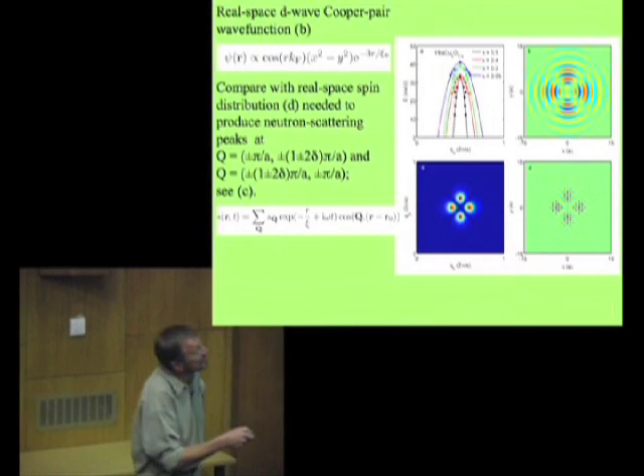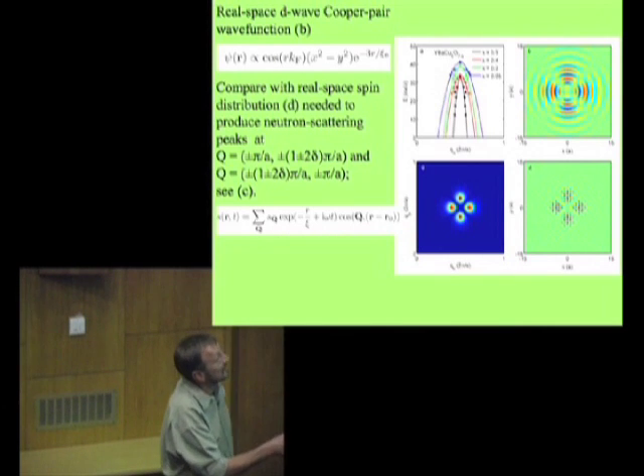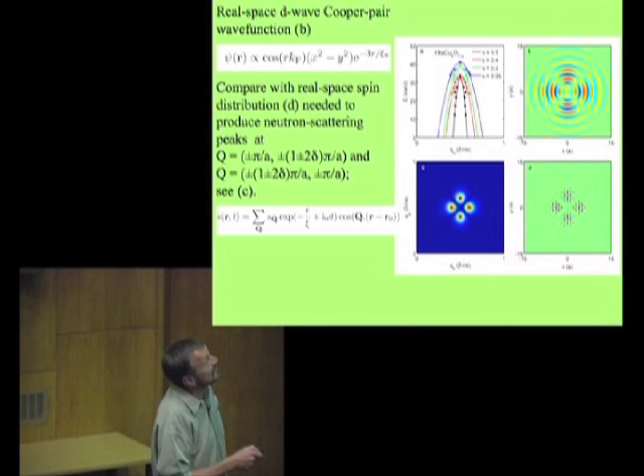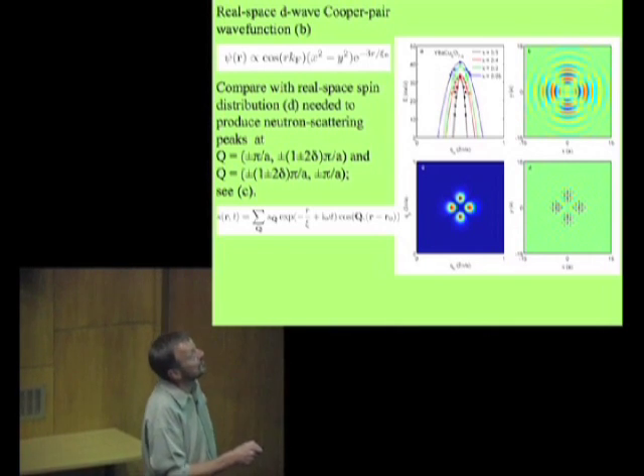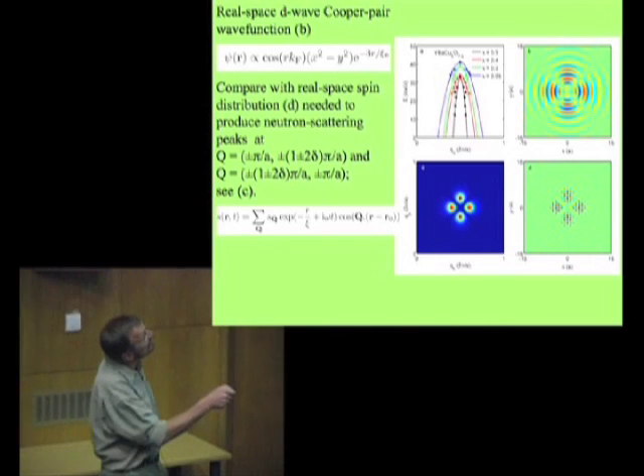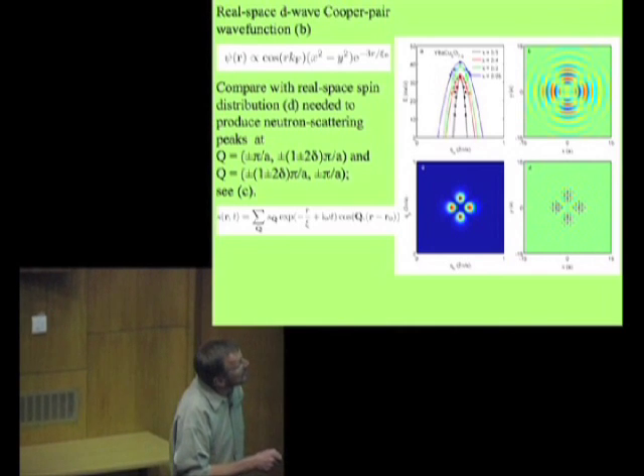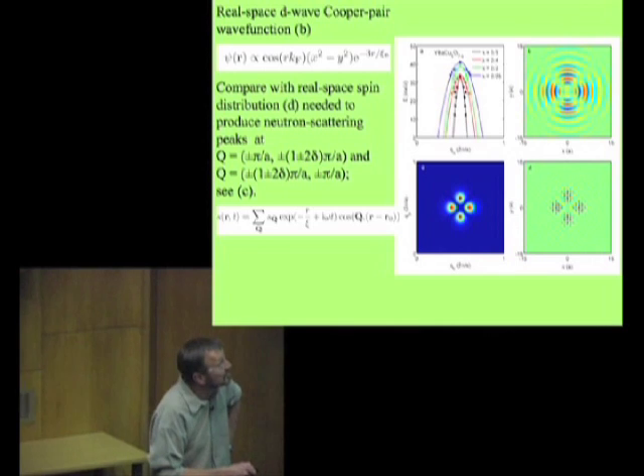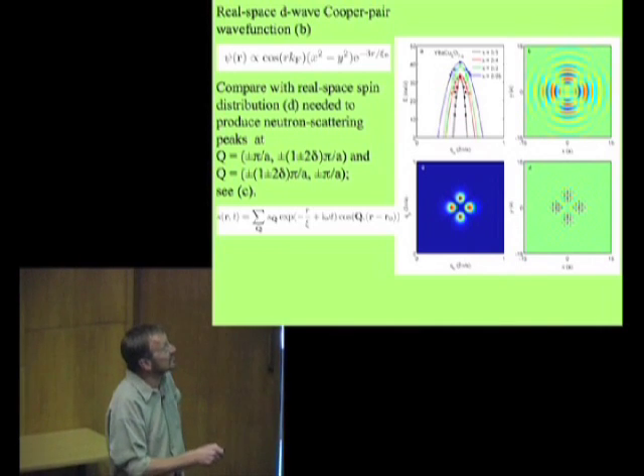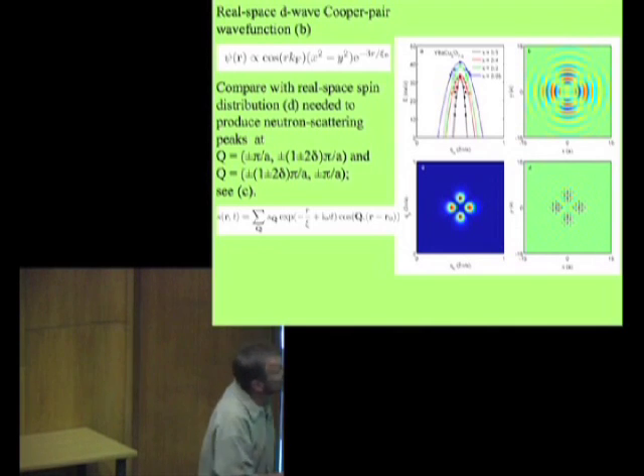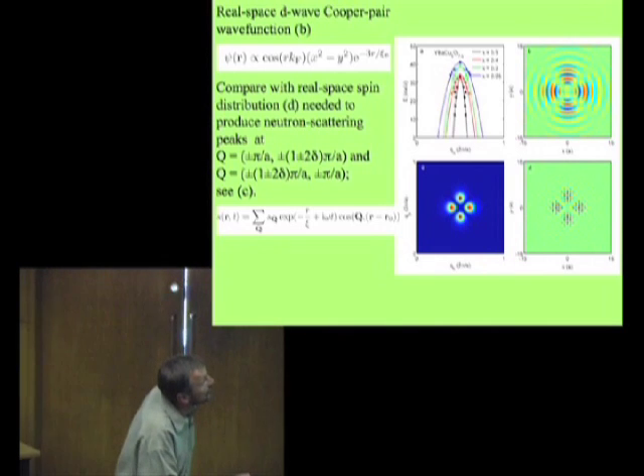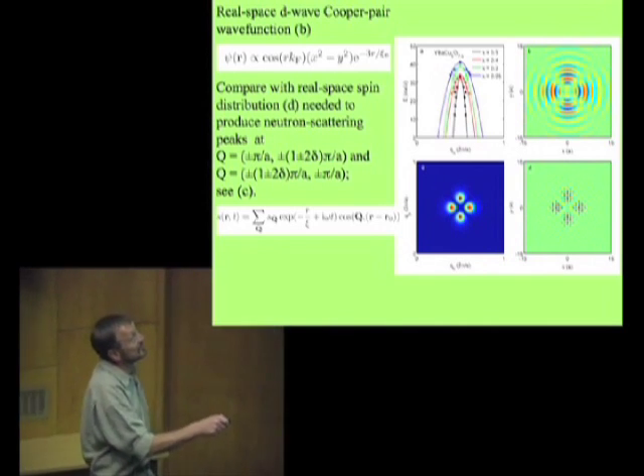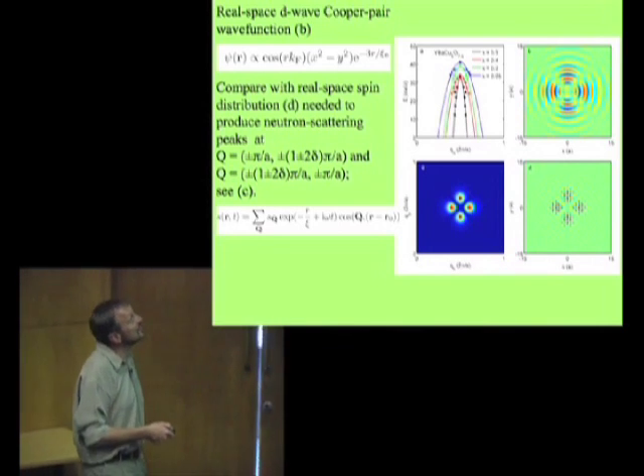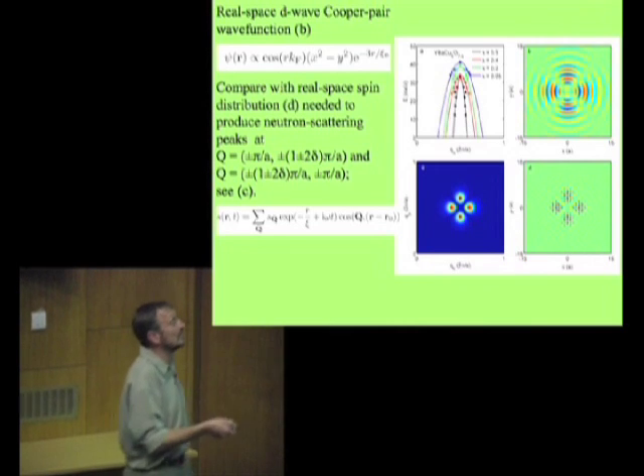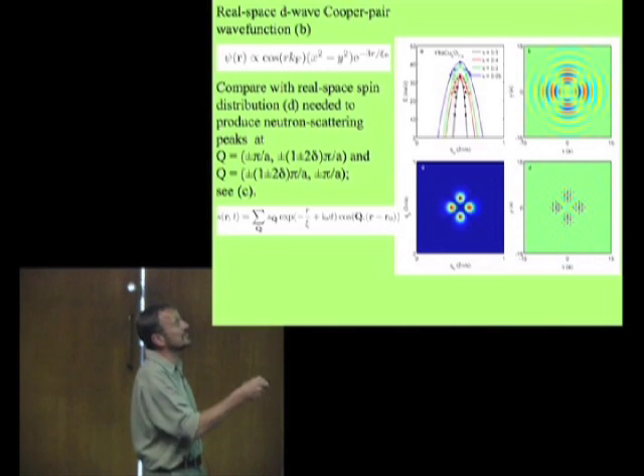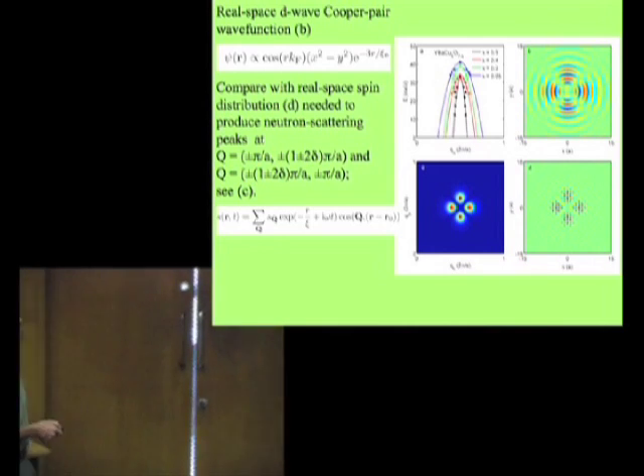The intriguing thing about this is the functional form of the spin density that gives us that neutron scattering. It looks very, very like the D-wave Cooper pair wave function. This is the D-wave Cooper pair wave function plotted in real space, this thing up here. It looks even more like it if we take this and Fourier transform it in 2 dimensions into real space. This is what you get when you take the spin distribution and plot its real space distribution here, and you can see that you even get the same phases of spin distribution as the D-wave Cooper pair wave function has. So that was very interesting. So our next thought was, if the spin distribution that gives you the neutron scattering in the Fermi surface looks so much like the Cooper pair wave function, perhaps they're linked in some way.